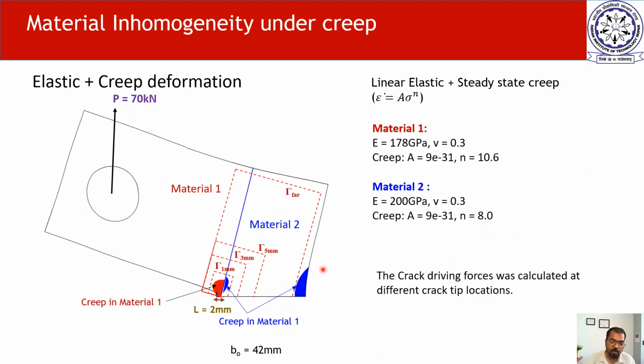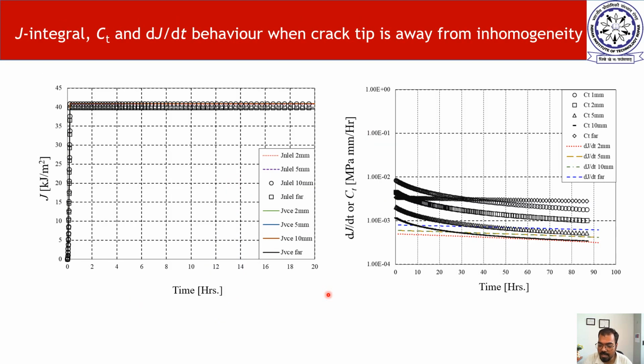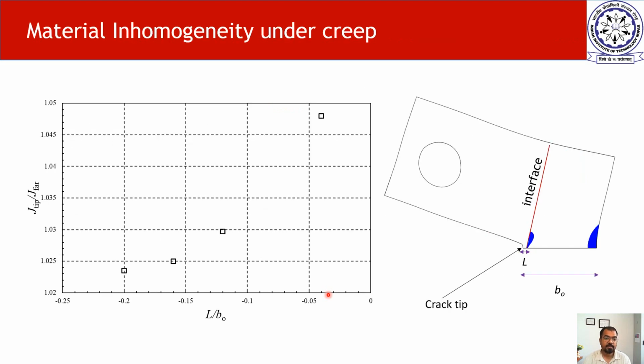So the far field node set might be hitting this blue zone, which is happening because of the creep deformation on the back side of the specimen, and that is different because that is a static deformation zone that is not moving with the crack tip. So that is why that is happening, but dJ/dt is showing more path independence than CT integral. And the effect on the crack driving force is calculated for a constant value of J_far at 17 hours.